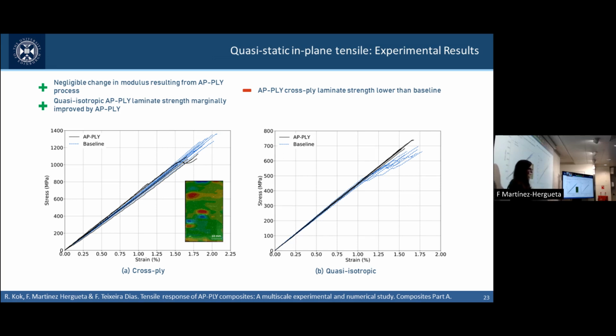In terms of strength, you find different answers when you go for different laminates. So for the first one, the cross-ply, what we obtain at this point is a lower strength. The lower strength is directly related to the undulation strain gradients. So what we find out is that these undulations are detrimental for strength. When they are subjected to axial loading, they are going to increase the local stresses on our tows, and they are going to trigger damage early.